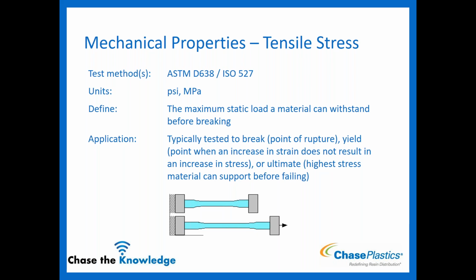And so again, if you watched my data sheet presentation, shameless plug, these were talked about as well. So tensile stress or tensile strength, if you hear it that way, is basically how much force we can pull in opposite directions to get the material to break. And so it's tested either at yield, where the stress does not increase with an increase in strain, or tested till break. You might also sometimes see ultimate, which is going to be the highest value of strength that it resisted. And so these values are typically given in PSI or MPa.